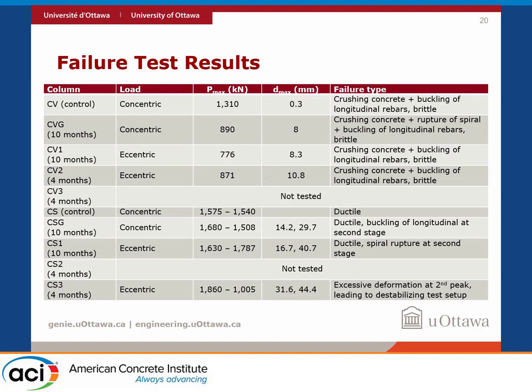We can see that the axial capacity of those columns was much reduced, and the deformation was also increased. In general, the failure type was brittle, with crushing of the concrete and buckling of the longitudinal reinforcement. And for the other set of columns, we observed that they were able to keep the confinement in spite of the loosening of the concrete cover at reaching the first peak, and their failure was actually quite ductile.